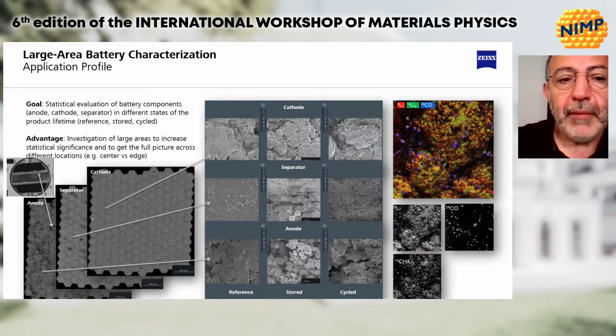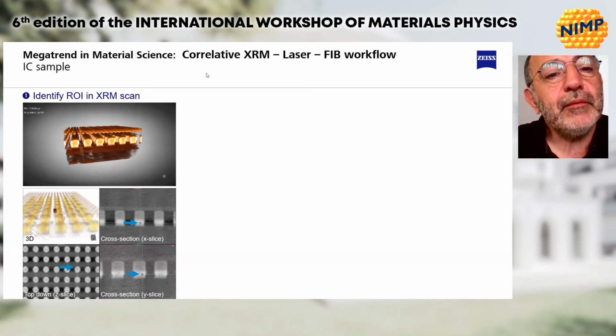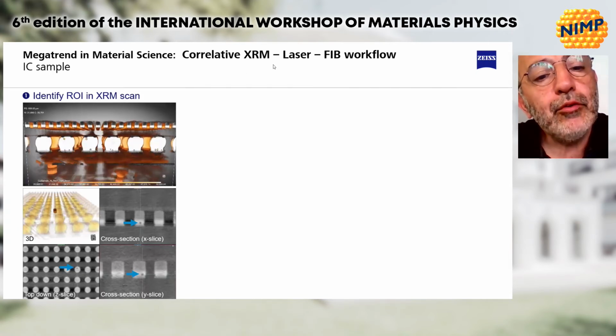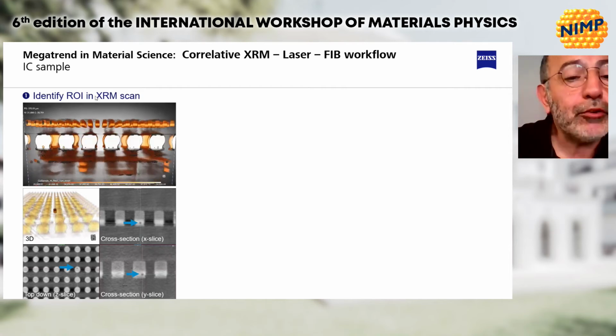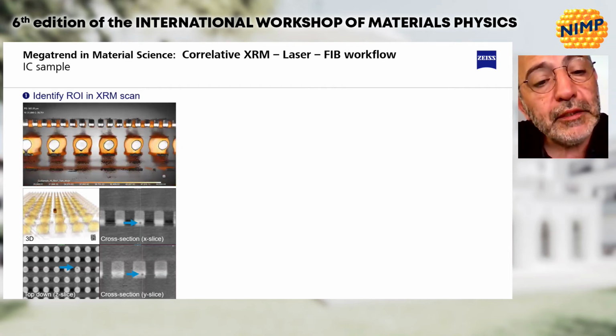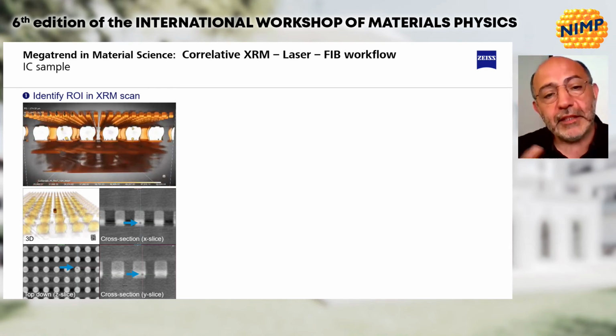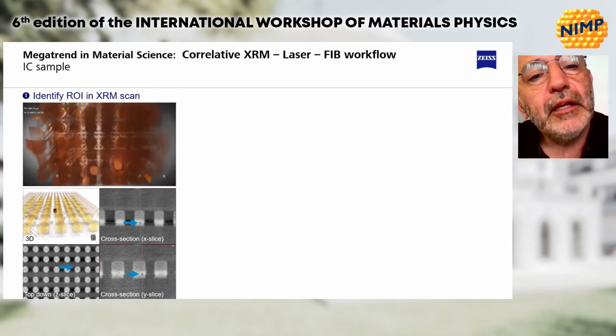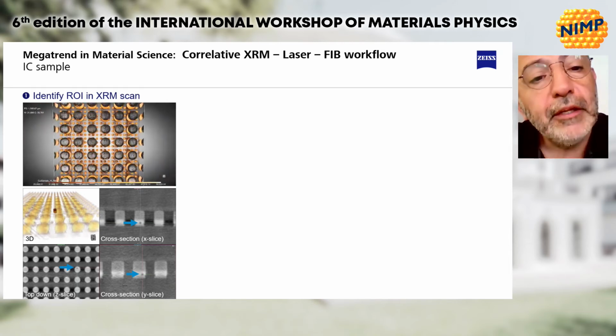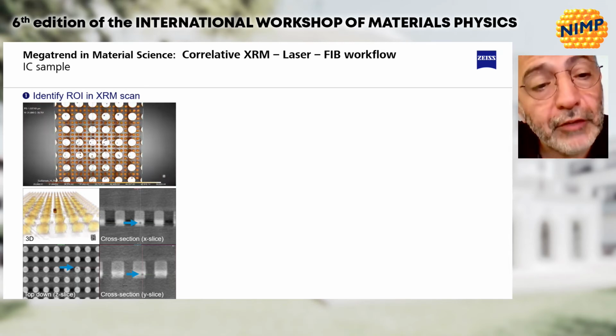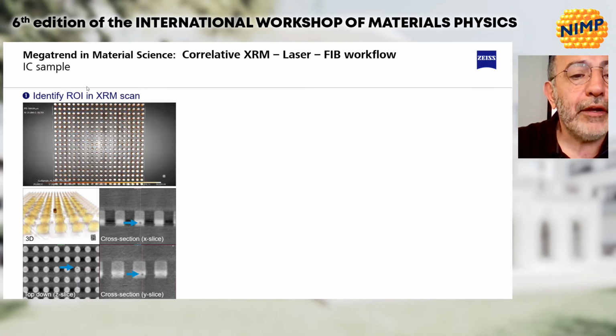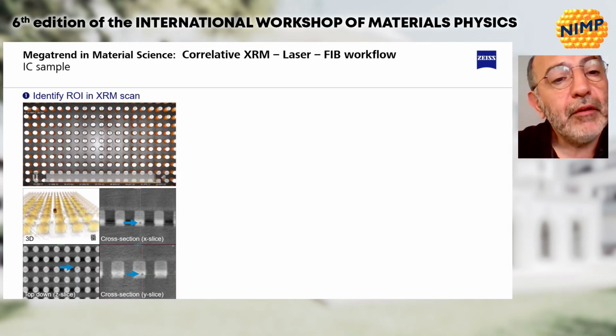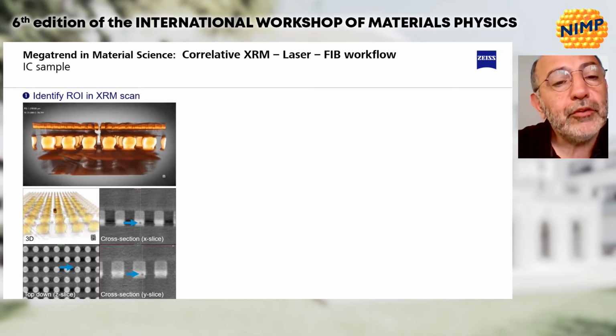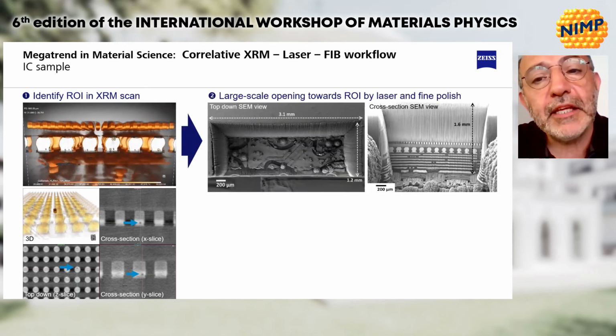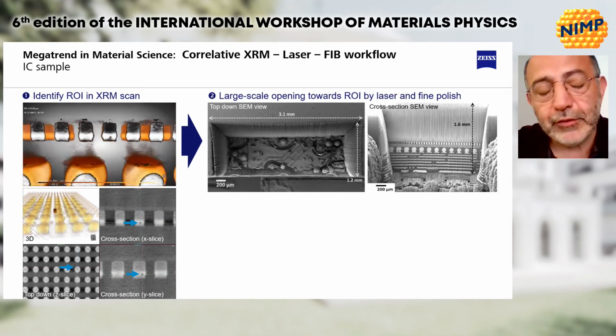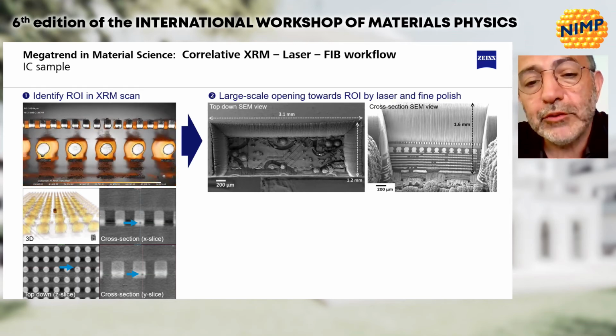in images. And another example here is what we see here. This is a correlation example using X-ray modality, or synchrotron if you want, just to identify in a huge sample, in this case a full microchip, the area of interest, the ROI that you want to finally analyze in higher resolution. And once you identify the regions of interest with this XRM, then you move to the next modality, which in this case is the cross beam, also the same technology, very well known as dual beam technology.